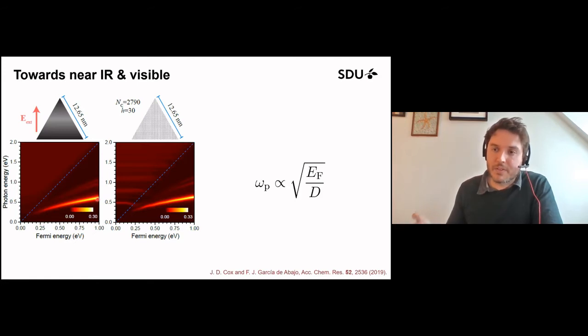So this is a good idea in general, but when you get to really small sizes, you start to run into issues because you have to deal with quantum mechanical effects that play a really important role in the optical response of these small islands, right? So for this 10 nanometer triangle, just as an example, you can already see a few differences between a model where you predict it as just a uniform homogeneous material that's shaped like a triangle, and you solve electromagnetic equations that describe it.